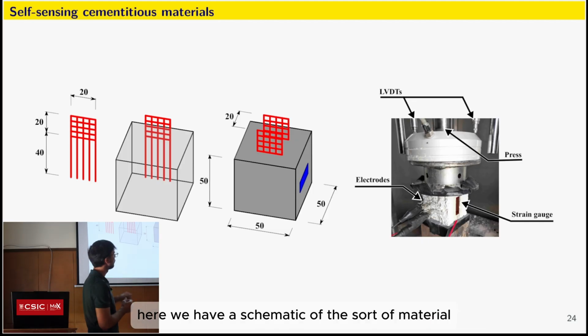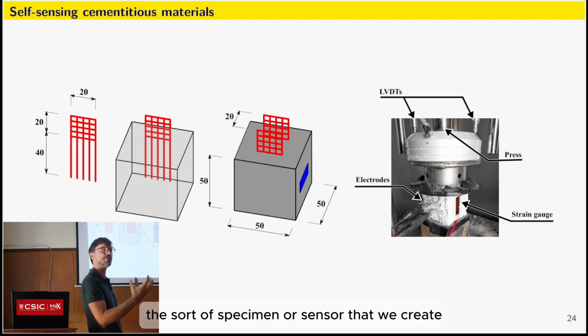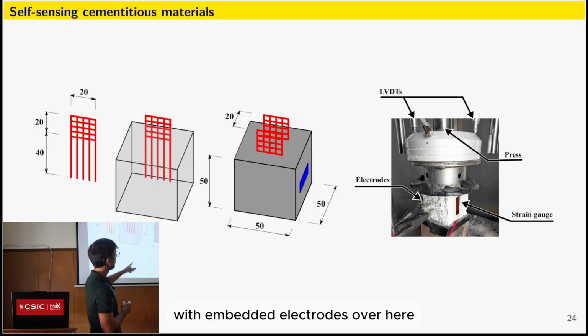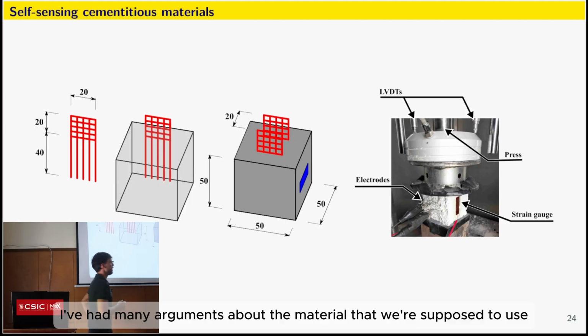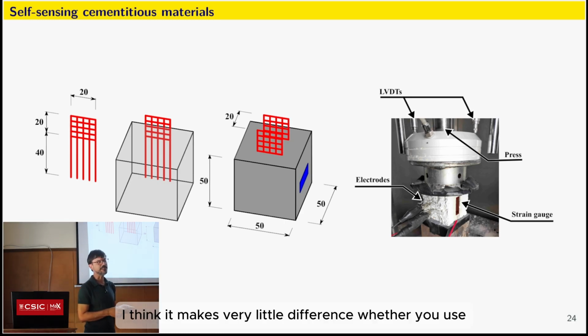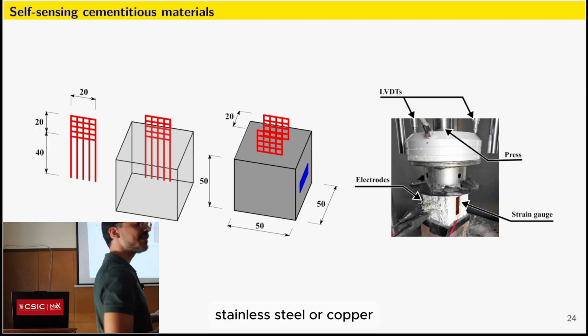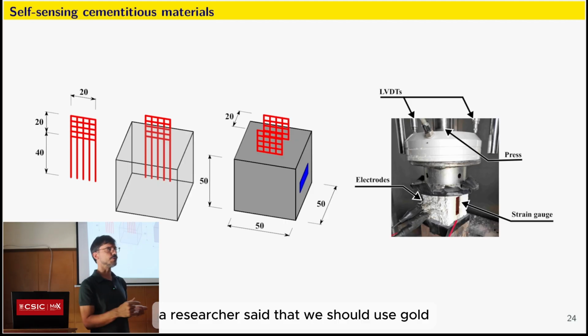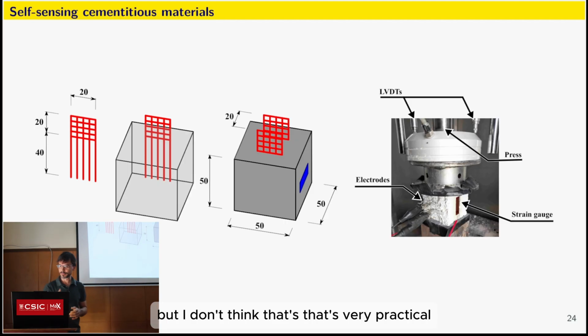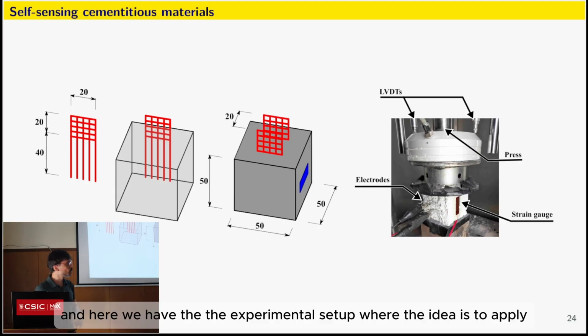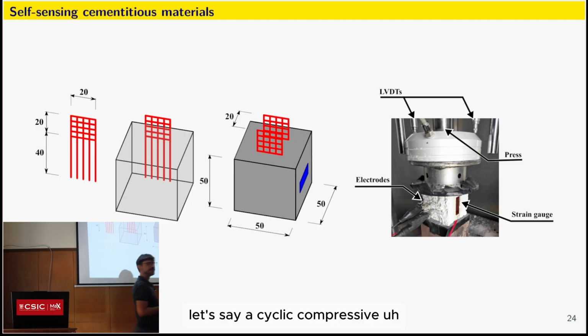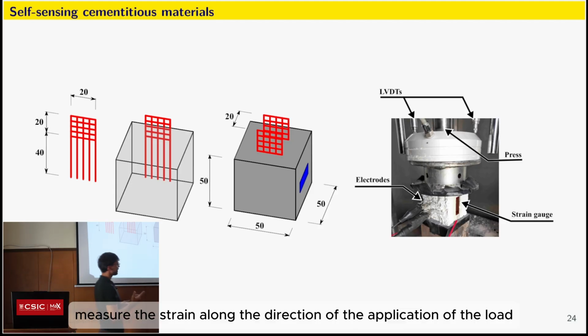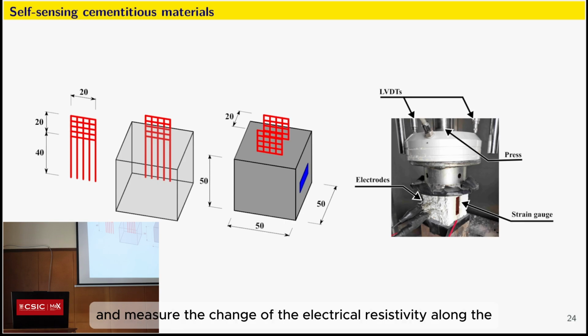Here we have a schematic of the sort of specimen or sensor that we create, with embedded electrodes over here. I've had many arguments about the material that we're supposed to use. I think it makes very little difference whether you use stainless steel or copper. A researcher said that we should use gold, but I don't think that's very practical. And here we have the experimental setup, where the idea is to apply a cyclic compressive load, measure the strain along the direction of the application of the load, and measure the change of the electrical resistivity along this direction.